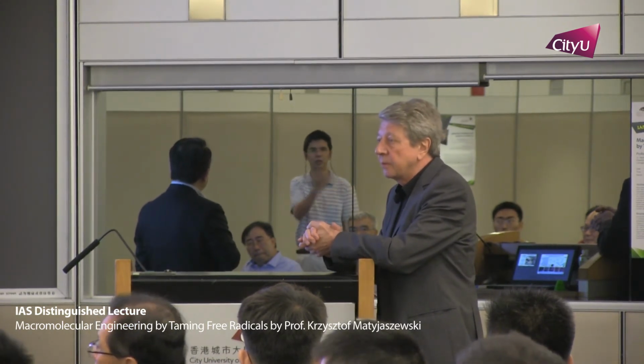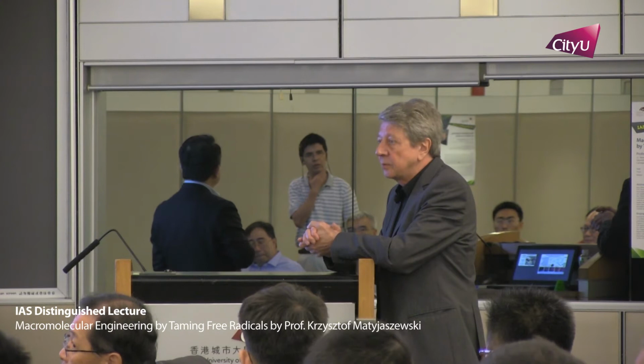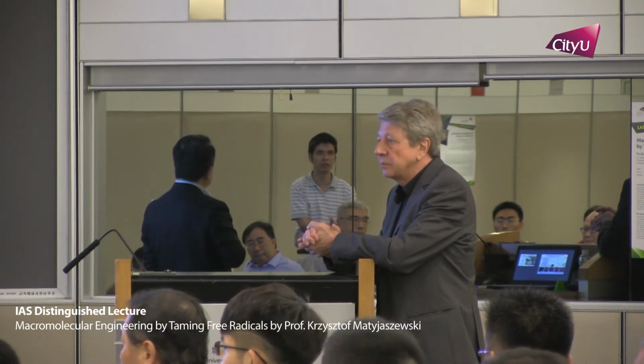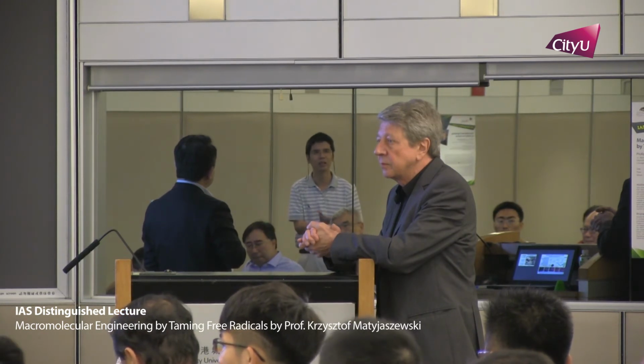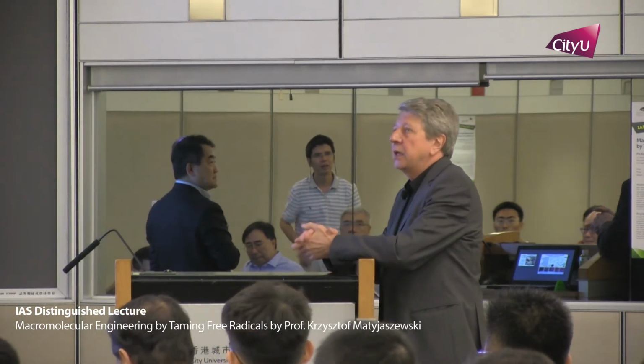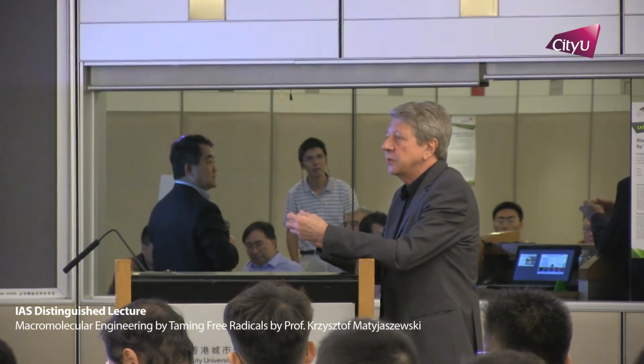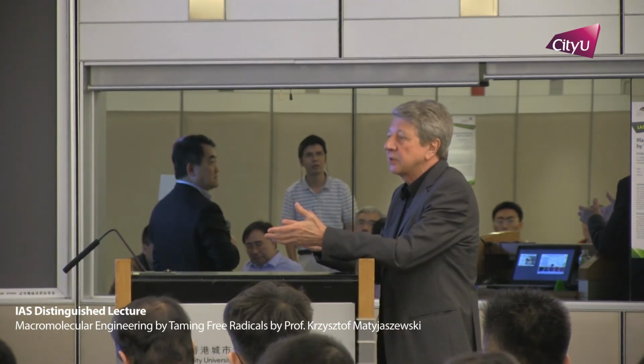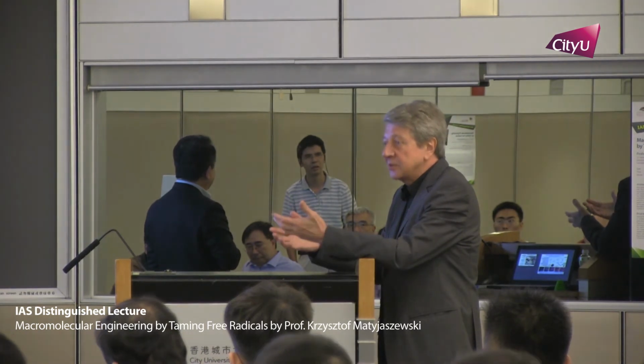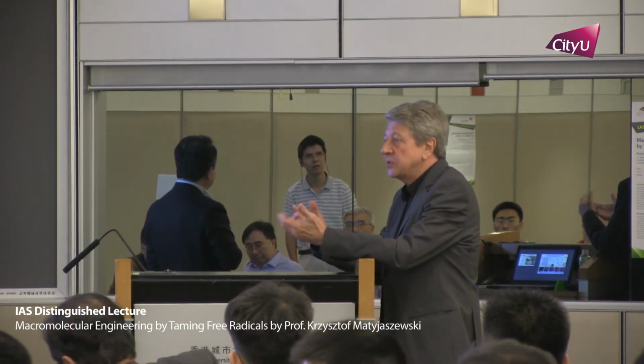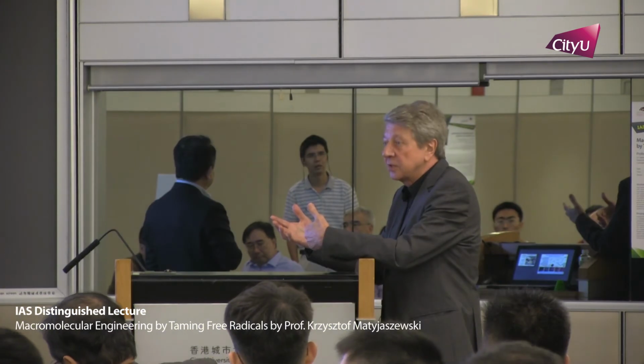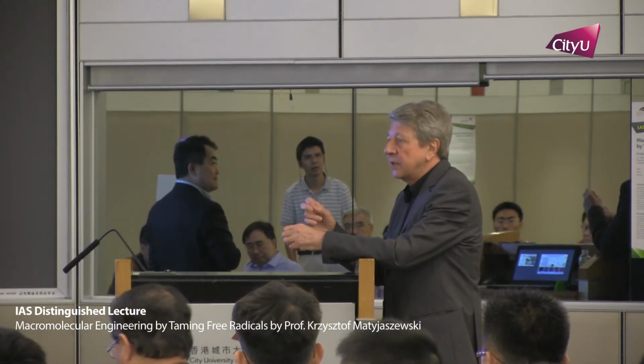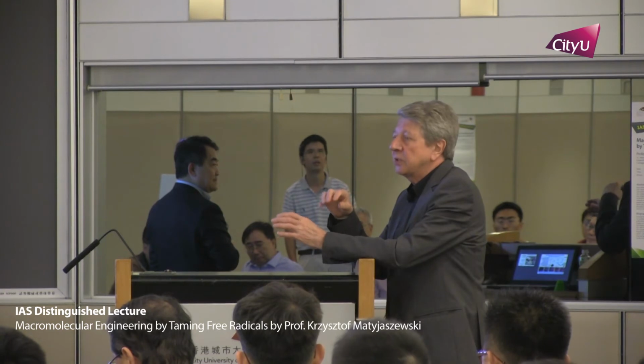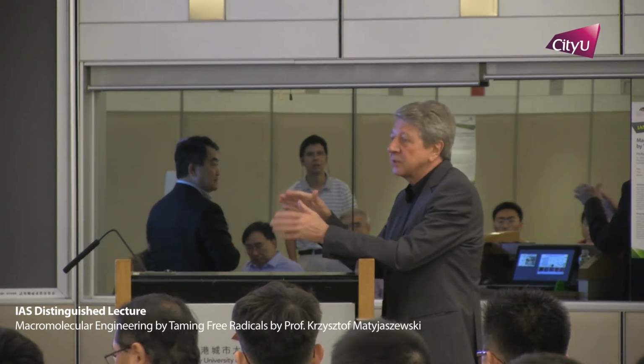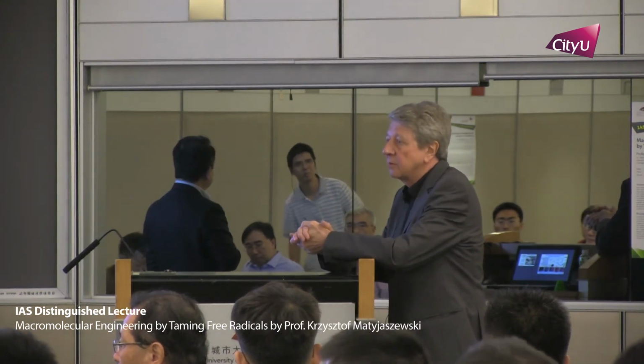So you think if you have electron transfer, then it should happen from the negative surface. Yes. Then you consider the positive surface is relatively inactive in this process. I think so, but also you need to do something with these electrons later, right? So you need a balance, electrostatic balance. So if this is reduced, something has to be oxidized. And in fact, we use excess of the ligand, these amines, and these amines can form radical cations in order to balance everything together. Good, thank you.